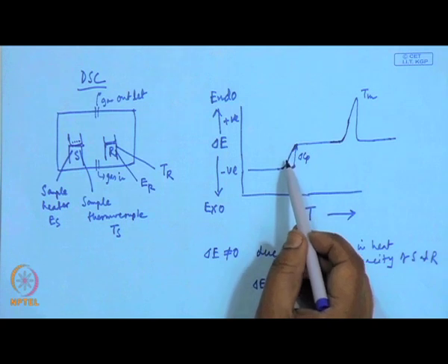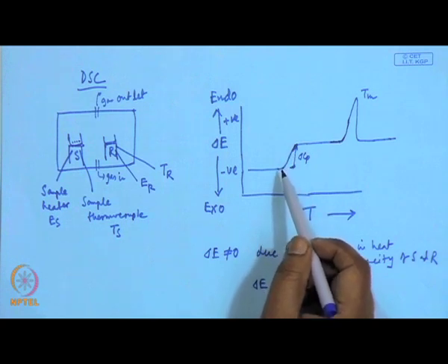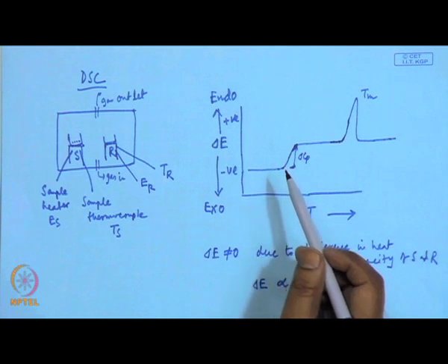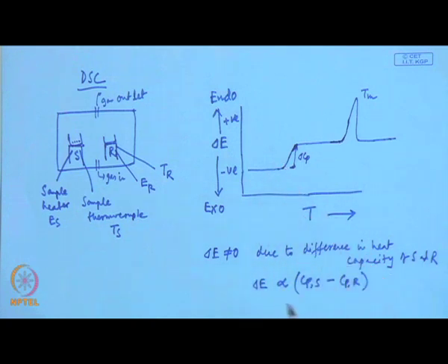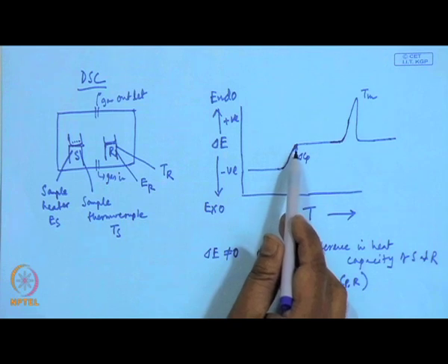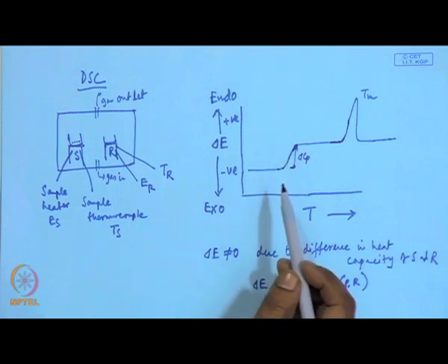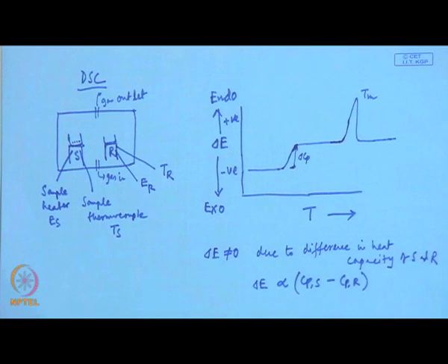and ideally this should be a sharp increase here, but as all of us know, the polymer sample consists of many chains of different length. So, the Tg corresponding to each chain is different. That is why we get a broad nature of this transition, because each higher size polymer will have a slightly higher Tg compared to a polymer chain having lower size.